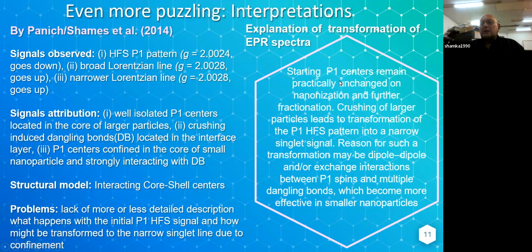This is our explanation of the transformation of the EPR spectrum. The initial P1 centers remain practically unchanged on nanonization and further fractioning. Crushing of larger particles leads to a transformation of the P1 signal into a narrow singlet line. A reason for such a transformation may be some new interactions there, dipole-dipole or exchange interaction between P1 spins and multiple dangling bonds, which become more effective in smaller nanoparticles.